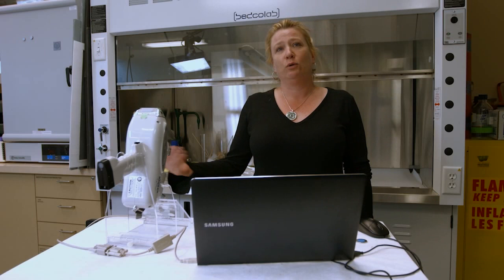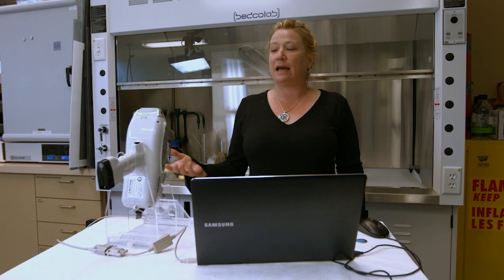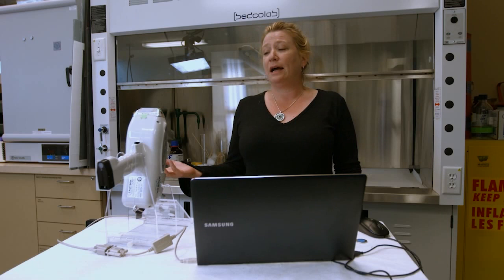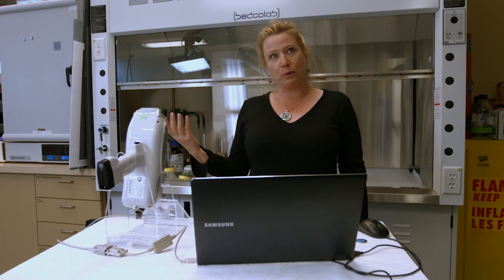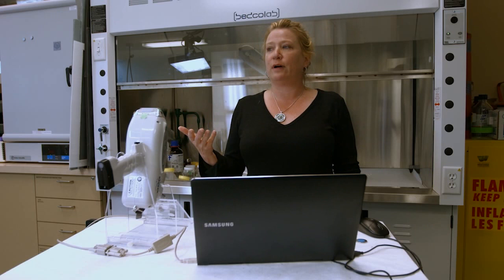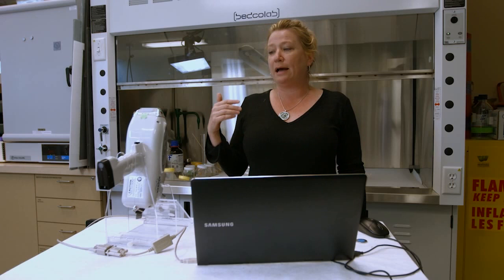I'm working with our portable XRF unit, which is an X-ray fluorescence dispersion analytical piece of equipment. What it does is it uses X-rays to determine the elemental analysis of certain materials. At the museum, one application is you can determine the alloy content of different metals, like coppers. If you're trying to source the original source of a copper object, you can look at the chemical breakdown and the ratios of different metals in the copper and source where it comes from.